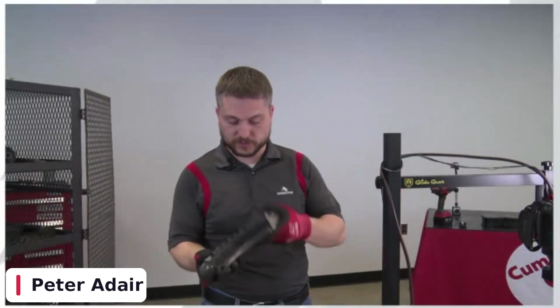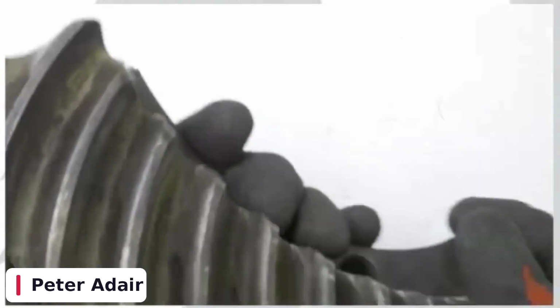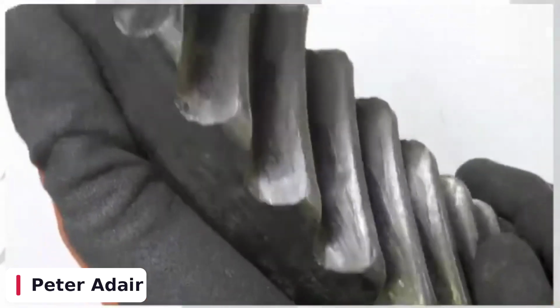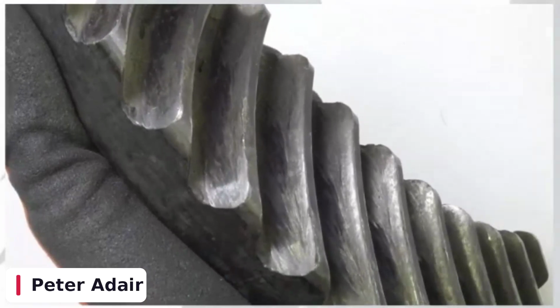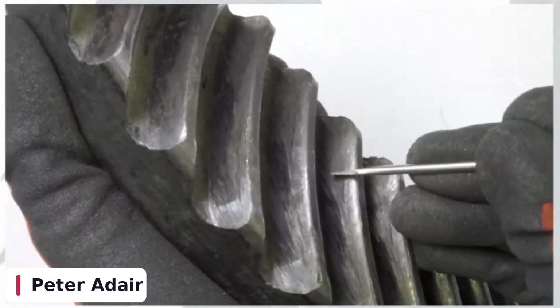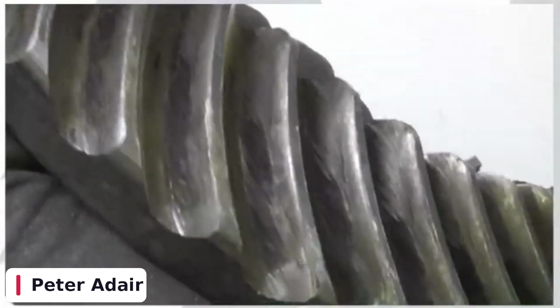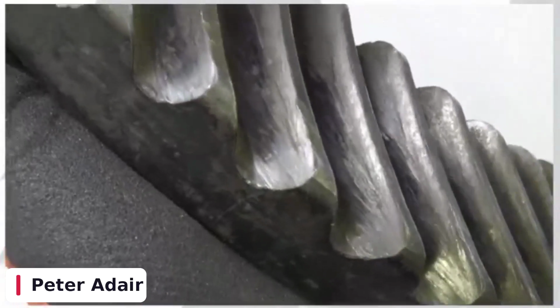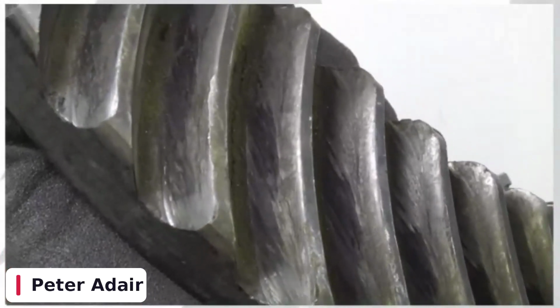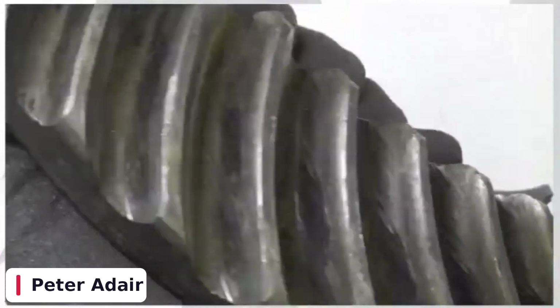Wrong, depleted or wrong lubricant, essentially on that one. So what happens with the low lubricant? The one major thing we're going to get with low lubricant is we're still going to get the crow's footing, which I'm going to show you, but we're going to get an additive on top of that. So let's go to camera 2. So we can see on this example, I have the crow's footing. I have the really deep grooving and scuffing into the gear teeth. And this one's going to be a lot deeper and way more prevalent. And the main reason is this was low and depleted.